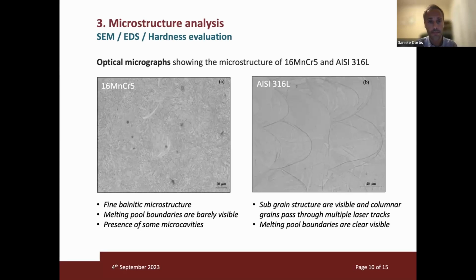This bainitic structure is sometimes common with the SLM process with respect to the martensitic structure, of course, because probably the solidification does not follow exactly the standard graph that we know. On the right, there is the austenitic structure of the AISI 316. Here, on the other hand, you can see the structure of the grain and the multiple laser tracks. It's a much clearer figure that confirms the literature of this material, which was one of the first printed with this technology.